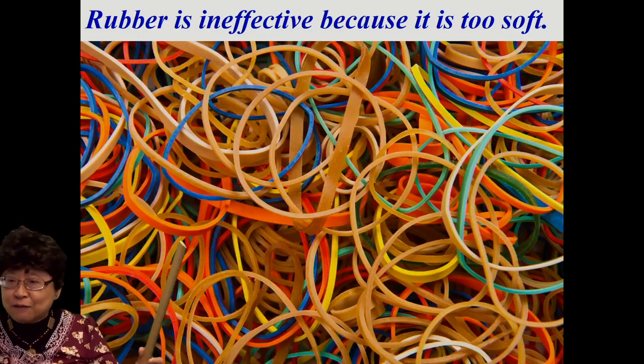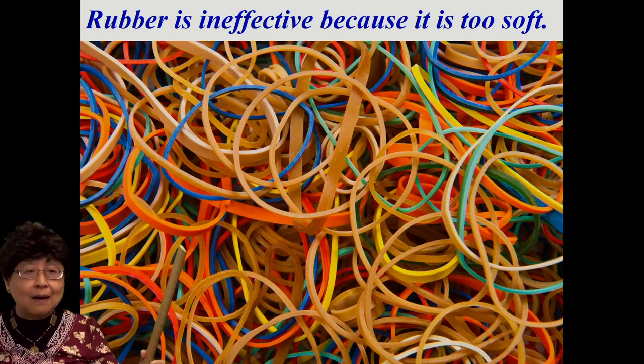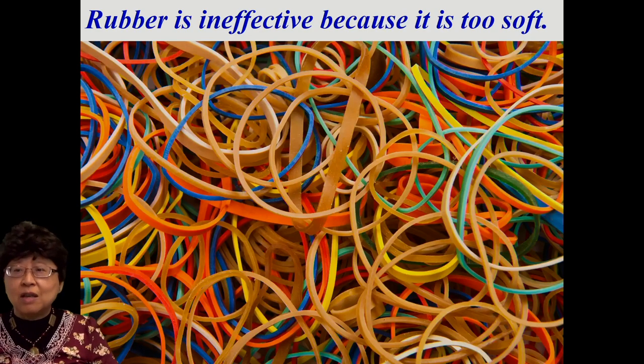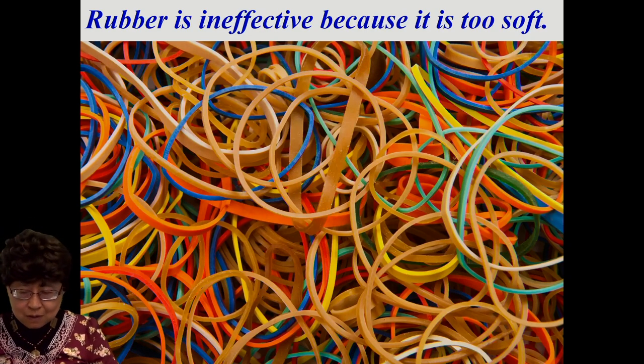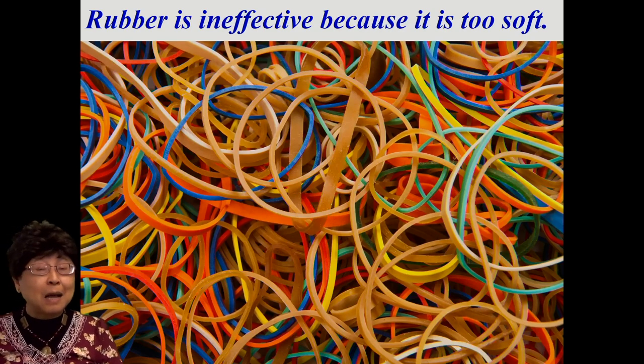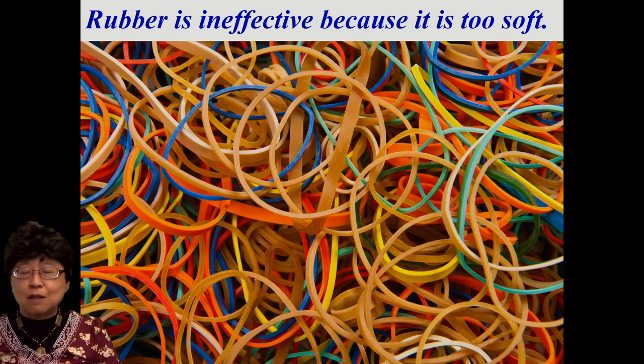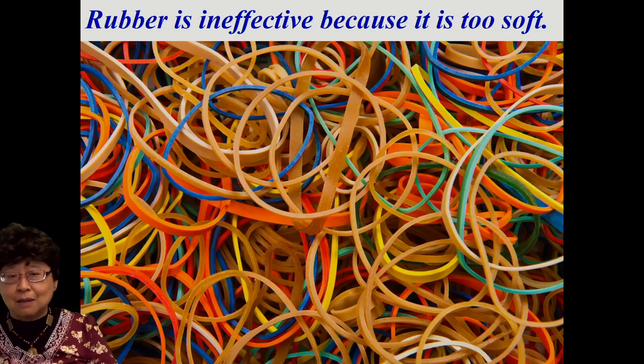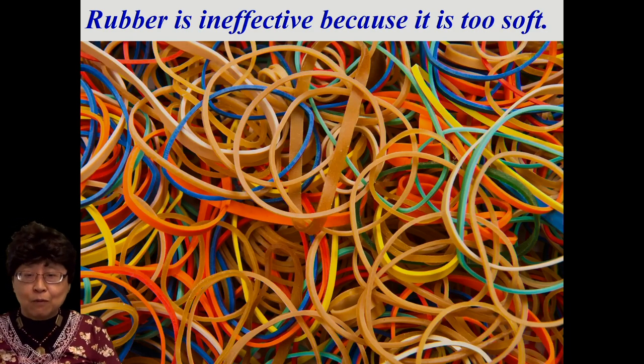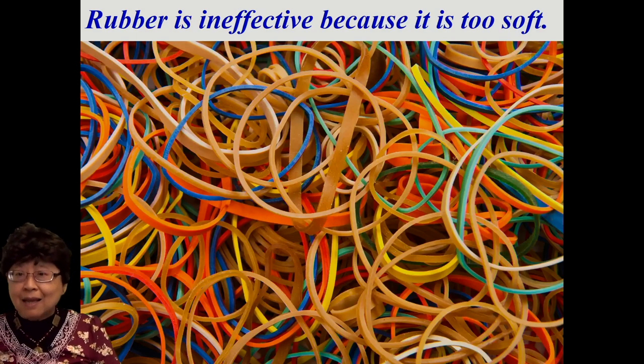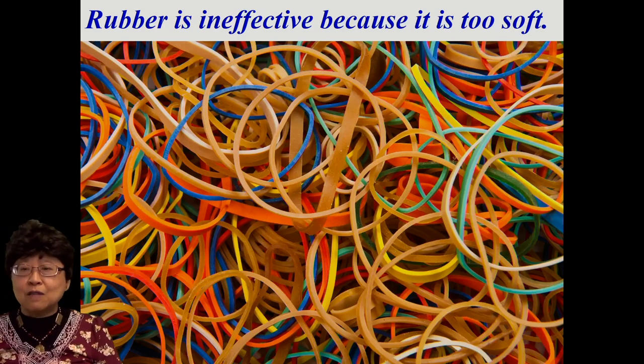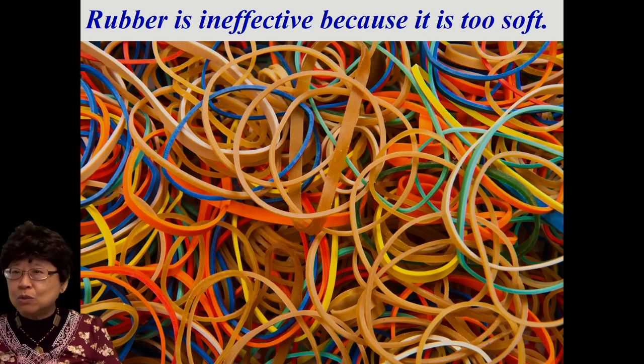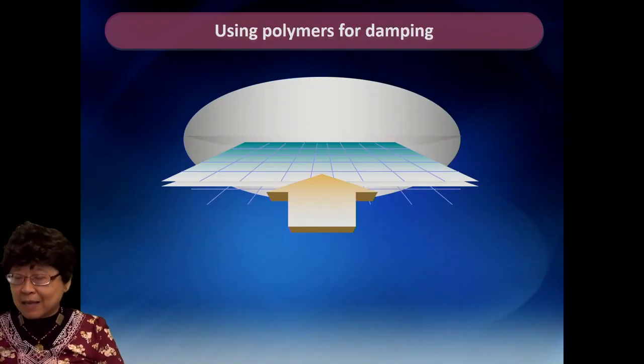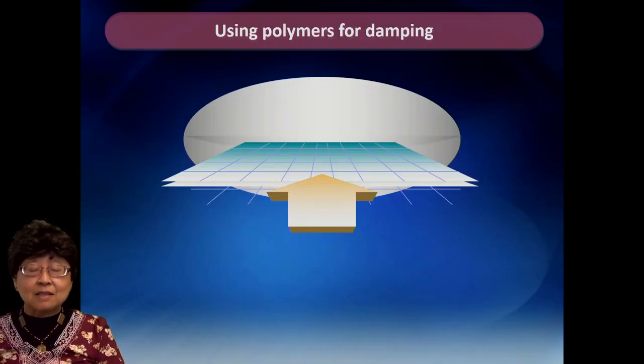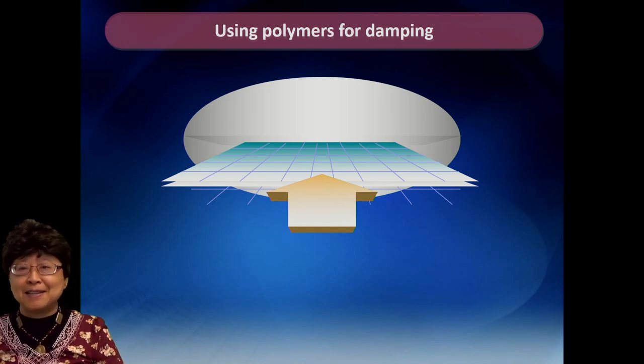However, rubber is ineffective for removing the mechanical energy because it is too soft. Okay? The energy is like force times distance, right? If it's too soft, the force is tiny, even though the distance is a lot. And so the product, force times distance, is still too tiny. Because rubber is too soft, it's not able to really dampen, not able to dissipate the mechanical energy. It can act as a cushion which spreads the mechanical energy only.